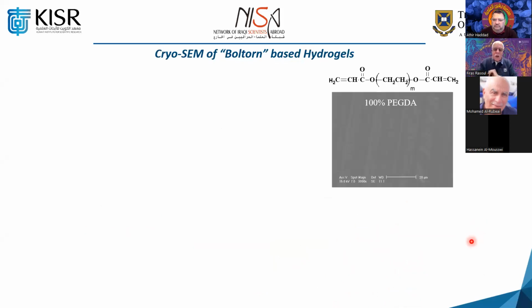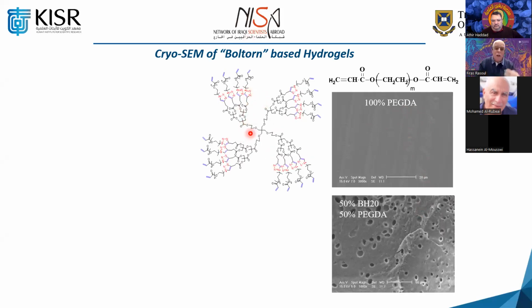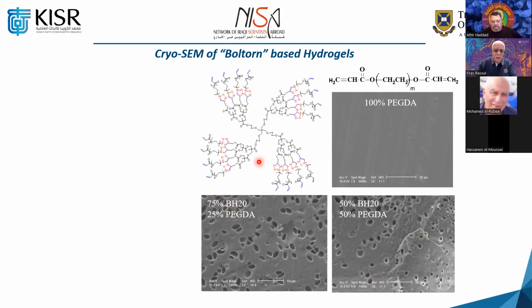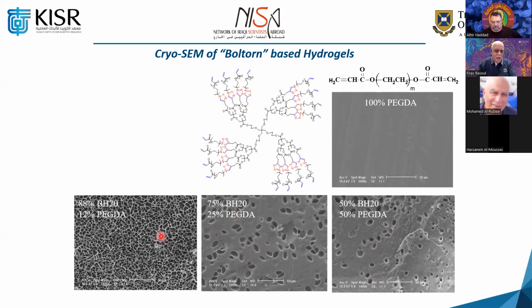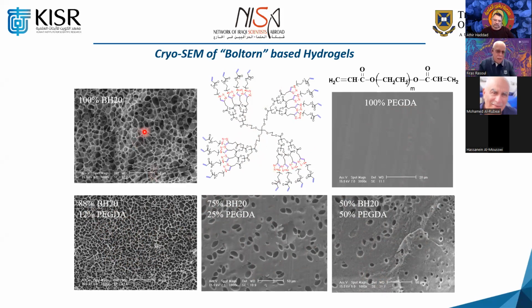And now I'll show you the porosity. This is a pure polyethylene glycol diacrylate. You could see there is no porosity. We start adding our compounds to it, the nanoparticle we made. At 50-50, you could see some porous structure start to appear. You increase it to 75 of that with 25 polyethylene glycol diacrylate, you see the porosity improving. And then when you go to 88% to 12%, you see it become very, very porous. If you use 100%, it is extremely porous.